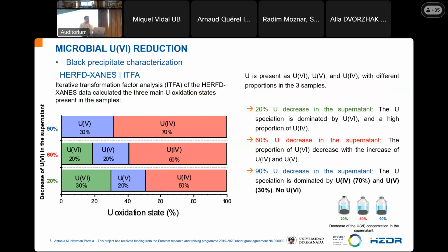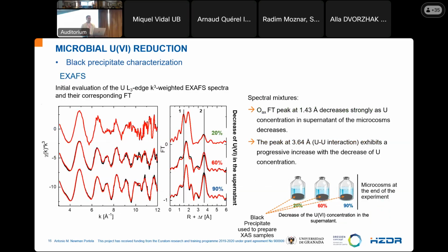These results are summarized in this slide, where thanks to the iterative transformation factor analysis of the HERFD-XANES data, we are able to calculate the dominance of the three oxidation states in all samples. I will continue focusing on the 90% uranium decrease in the supernatant, and the speciation is mainly dominated, as you can observe here, by uranium-4, 70%, and uranium-5, 30%, and no uranium-6 was measured. I will continue with the EXAFS data.